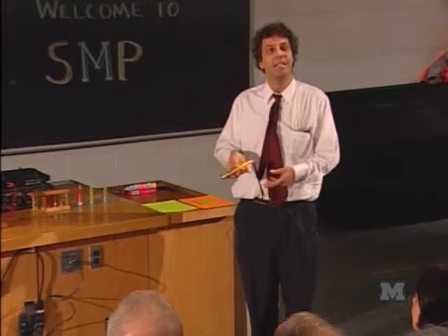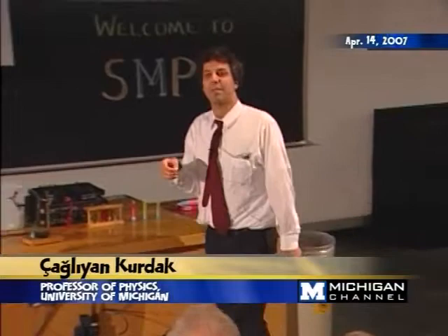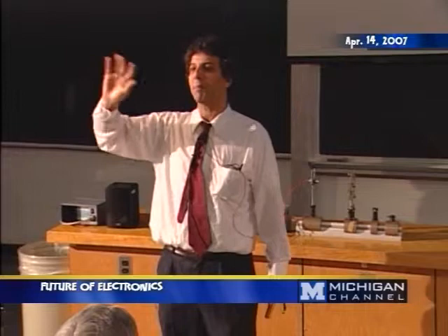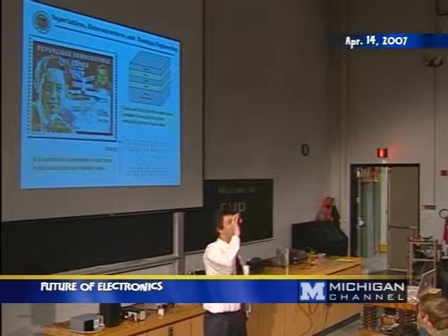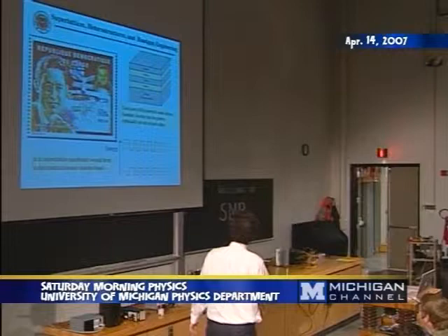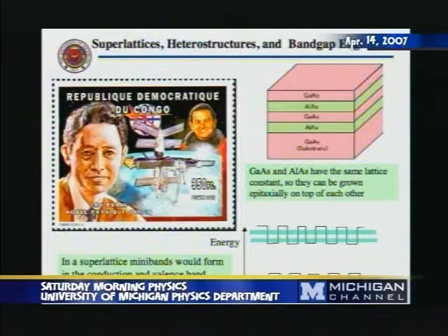He recognized that if you put them on top of each other, since they have exactly the same lattice constant, you can put them on top of each other without disorder. And remember, from silicon, we are not like chemists. Even 1%, even 0.001% disorder is unacceptable. We want high quality materials for semiconductors. So you have to have lattice matched materials, and this was possible in this material system because they had identical lattice constants.